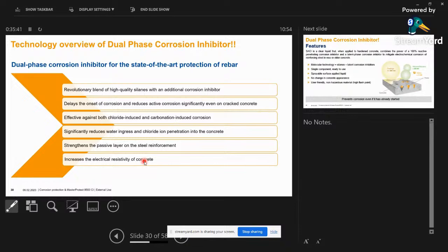Now, why do we use this? Why do we say that it should increase the electrical resistivity of the concrete? Because if the electrical resistivity of the concrete goes up after the application of this treatment, naturally you will see that the corrosion activity will come down, because it is inversely proportional. If the resistivity is higher, corrosion activity is lower.